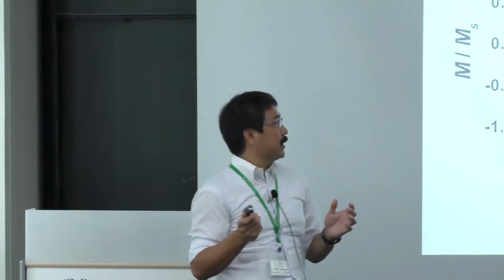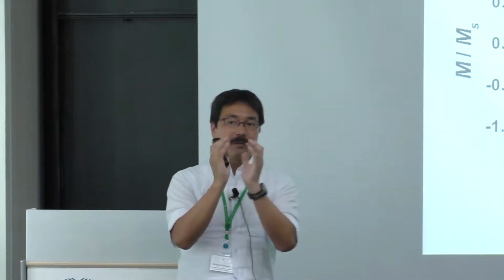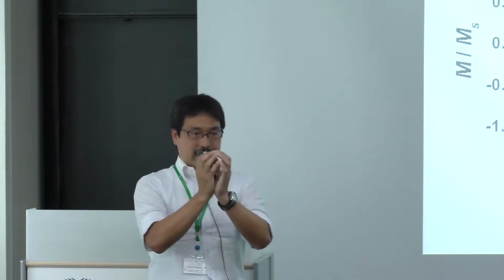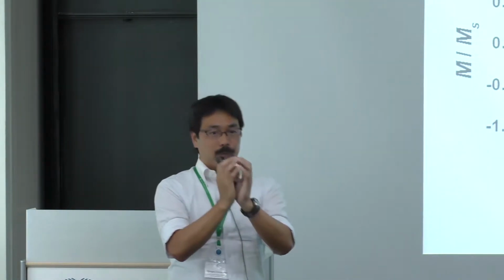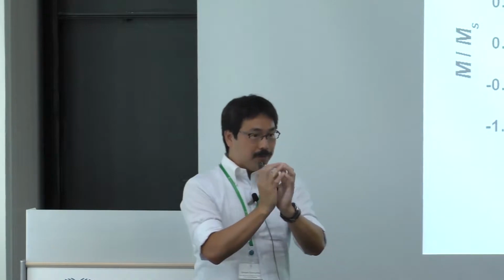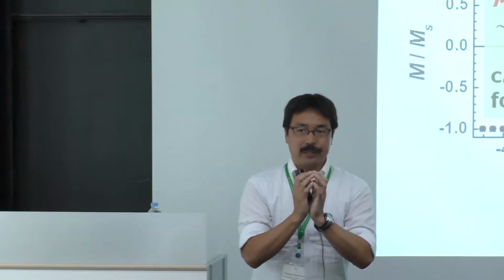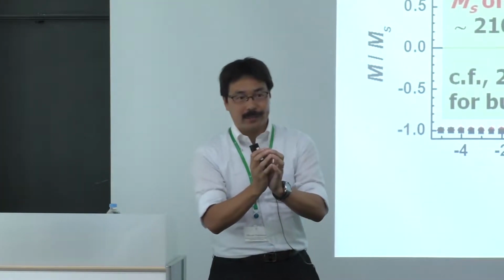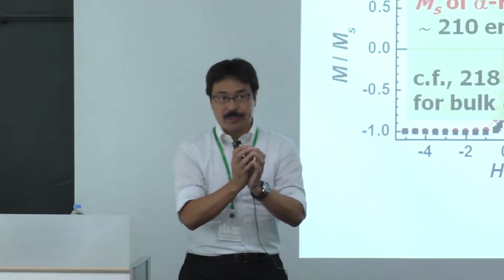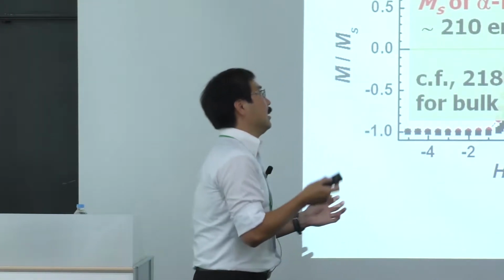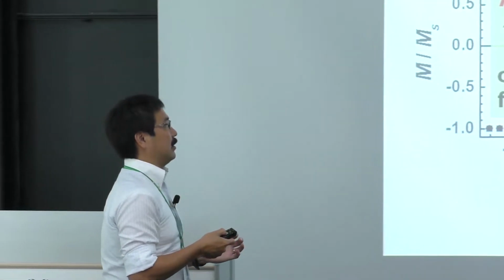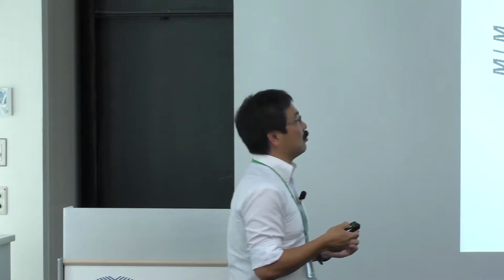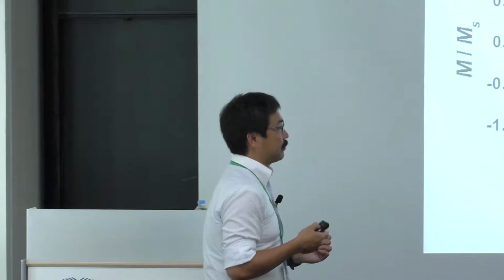This is because, as I explained, the surface of the alpha iron nanoparticle is coated with silica, but the silica is in an amorphous state. As you know, amorphous silica has many open micropores through which gaseous molecules can pass, so our nanoparticles are oxidized in air even when coated with SiO2.